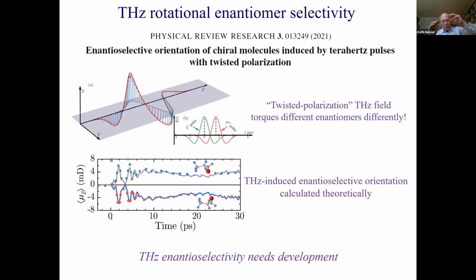Finally, in terms of one more example of what happens with terahertz fields and rotation, if I change the polarization of my terahertz field, so it starts out with a cycle like this and ends up with a cycle in the other direction, that exerts a unique torque on molecules. If I have chiral molecules, that torque is different for the different enantiomers. So the result after it's over is that the collection of two different enantiomers are actually oriented differently in space. That could be exploited for a unique kind of all-optical separation of different enantiomers. Now, that hasn't been done experimentally. These are theoretical calculations, but that's a possibility that would just be very, very exciting.